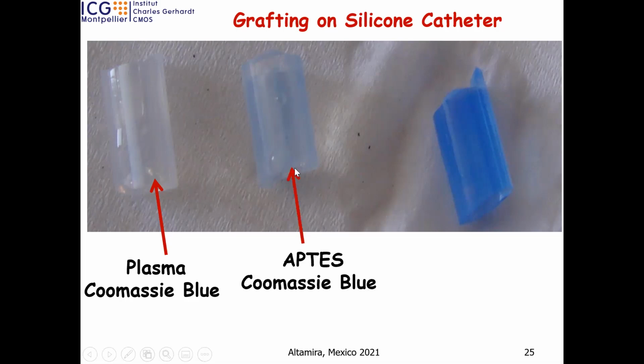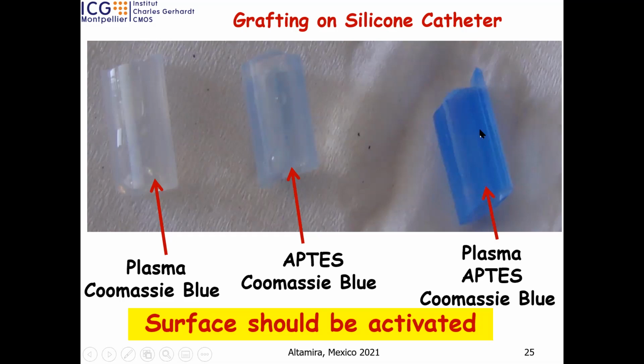The second one is without plasma. We make a dip coating of the catheter in the solution containing aminopropyl triethoxysilane and follow it by Coomassie blue. It's slightly blue, okay? So we immobilize some amino groups, but not enough. In the last one, you can see clearly it's blue, really, it's after plasma, followed by immobilization of aminopropyl triethoxysilane, and then Coomassie blue test.